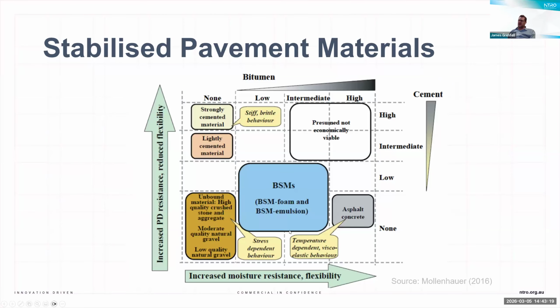So this time we're talking about this bluish area, bitumen stabilized materials. So foam and emulsion sit in this part. We're adding small amounts of bitumen and cementitious, or in this case, hydrated lime, to granular materials to improve their performance in terms of moisture resistance and also reducing their susceptibility to permanent deformation.